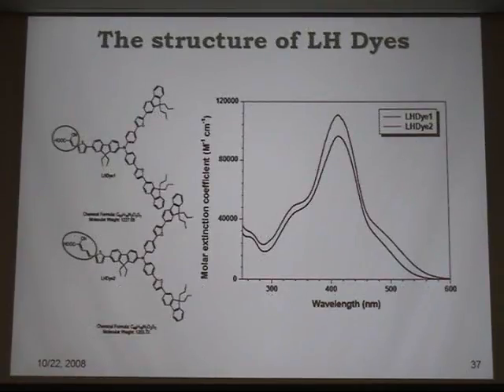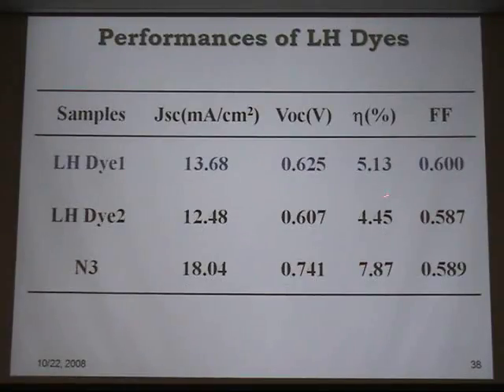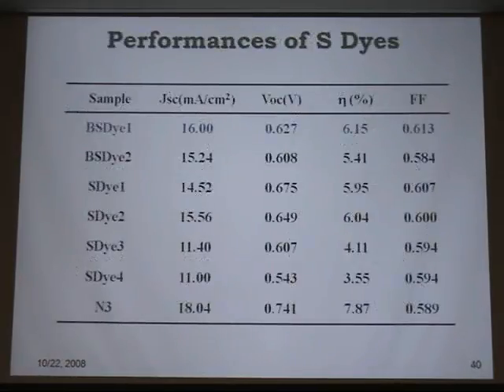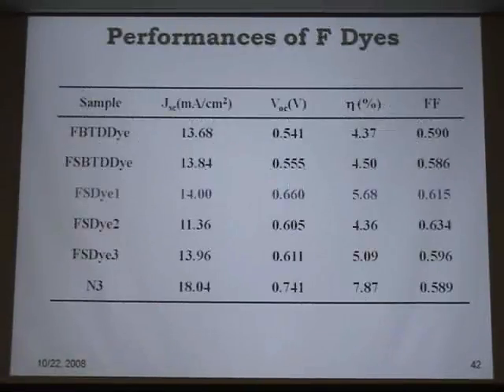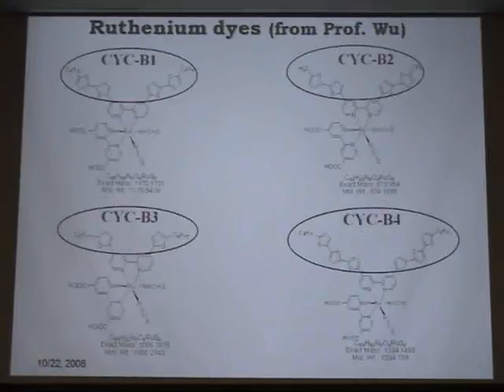Again, for a different dye, if you think number 2 will give the best performance according to this, that's probably wrong, because this one gives you the highest. So we have to correlate the performance not only with the absorption coefficients, but with the electron lifetime. I'm not going to show you too many dyes we synthesized, but let me get to one of the ruthenium dye systems. This is a dye system obtained from Professor Wu and his group.